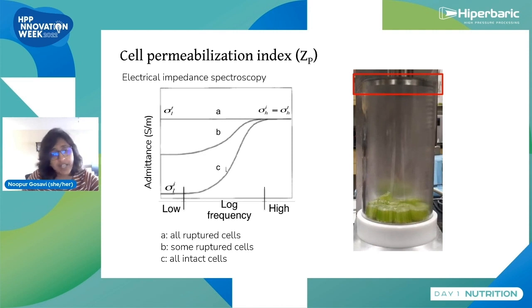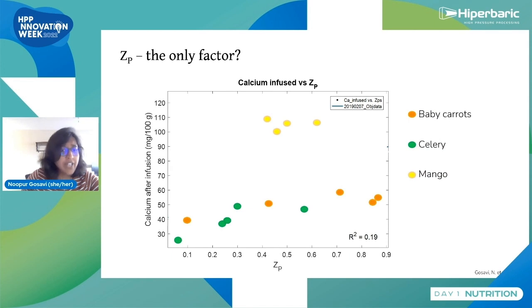So a lot of researchers hypothesize that the cell permeabilization index is the major reason why the infusion under high pressure is enhanced. But if that was the case, you will see that if we ignore the food matrix, there is no correlation between the ZP and the amount of calcium infused. In fact, if you look here, the amount of calcium infused for the same level of ZP in baby carrots and mango is significantly different, which tells us there is more work here that we need to understand.